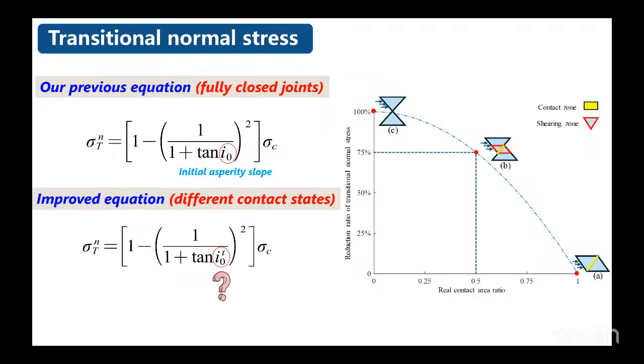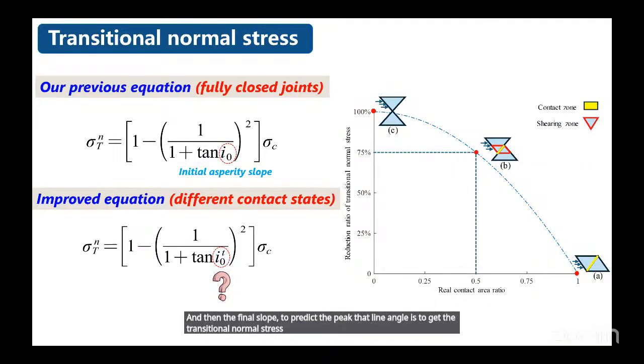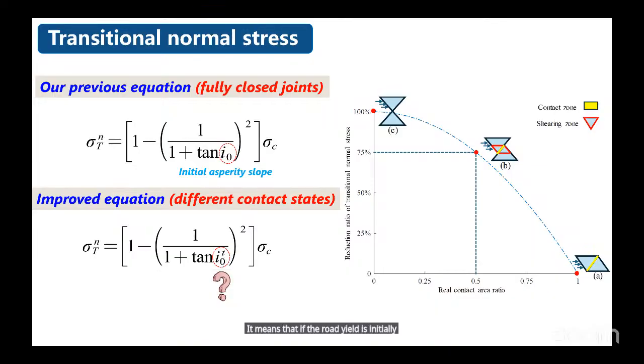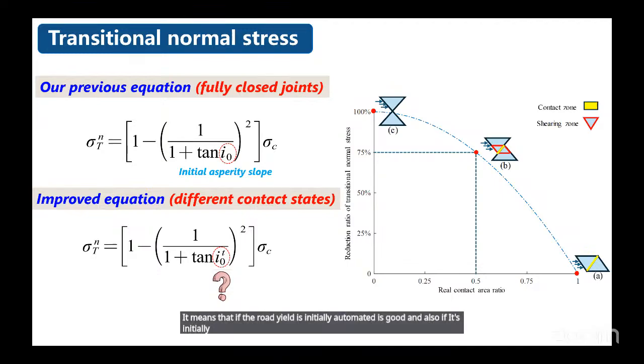And the final step to predict the peak shear strength is to get the transitional normal stress of the joints in different contact states. These contact states include both the initial contact state before normal loading and the contact state after normal loading prior to shear. It means that if the rock joint is initially mated, it works, and also if it is initially unmated and then mated after compression, it is also effective. And previously, we already proposed a nonlinear equation to predict the transitional normal stress as a function of the initial asperity slope and rock strength, but only for the fully closed rock joints.